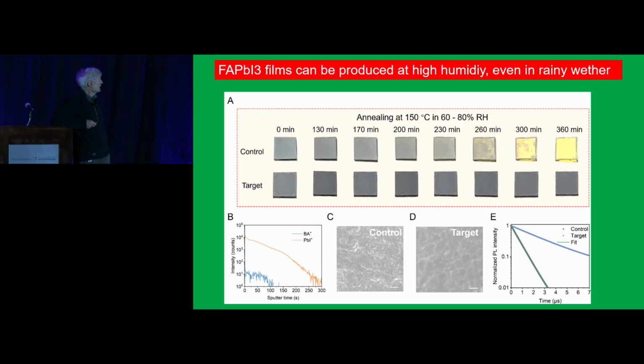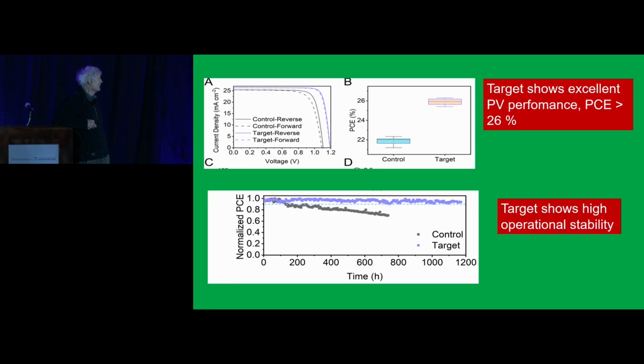And so you can see here we are heating the film at 150 degrees in 80% humidity. I mean, if you put your hand in a climate like that, I wish you good luck. And so these films survive under these conditions. So that allows making these devices even in rainy conditions. And stability-wise, you see very nice operational stability. Efficiency is over 26%. So the paper is submitted. Let's hope the referees will like it.